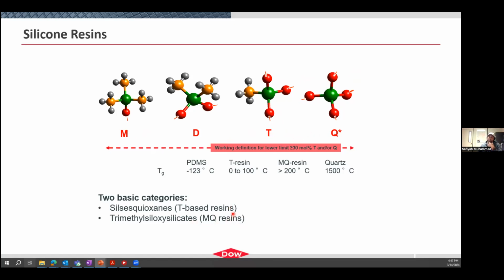And then you have a special type of silicone resins, which are called MQ resins, and they are made strictly of M units. And remember that M units can only bind once. So you have a Q structure that grows together and you end up capping it with M units. So now you have M on the surface. And so these types of materials are, again, usually solid-like materials. They have higher Tgs than PDMS, and MQ resin has an even higher glass transition temperature than T resins. And they exhibit some very, very cool properties. The reason why we use them is because they are more oxidized, so they are often more stable, right? Stable to heat and stable to degradation.